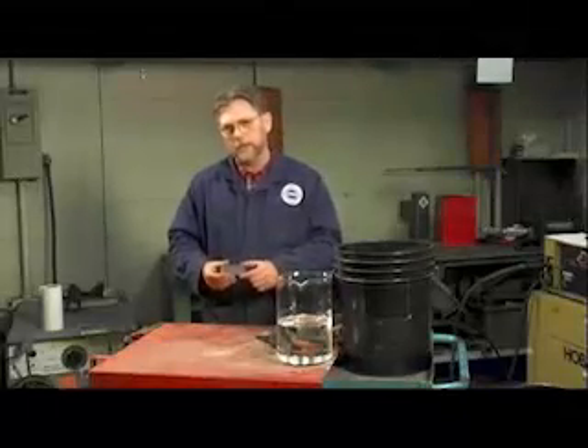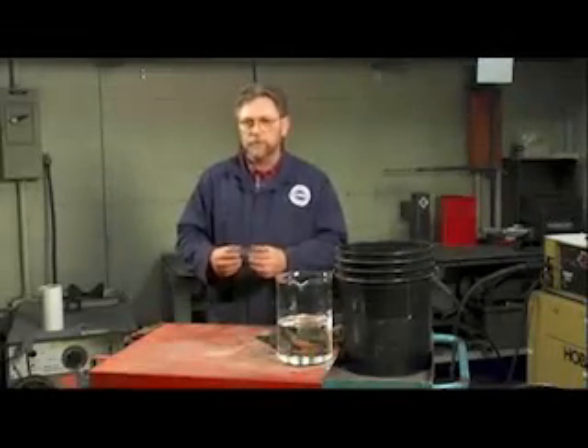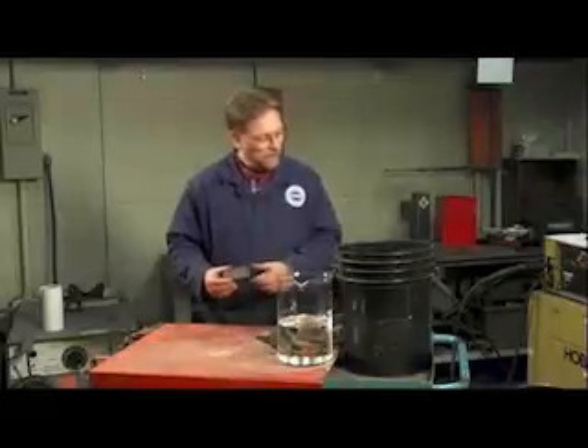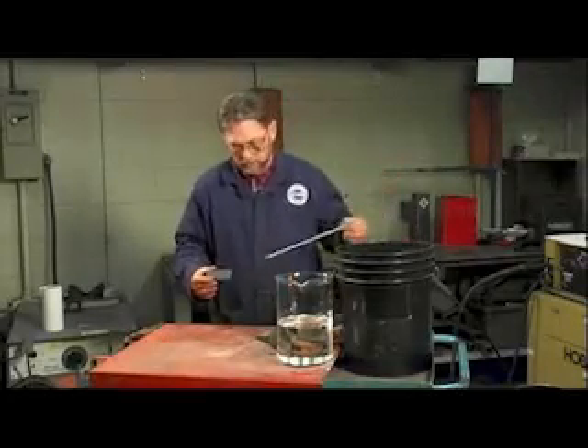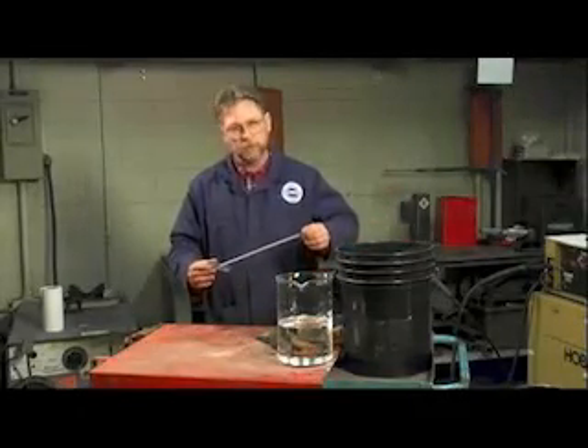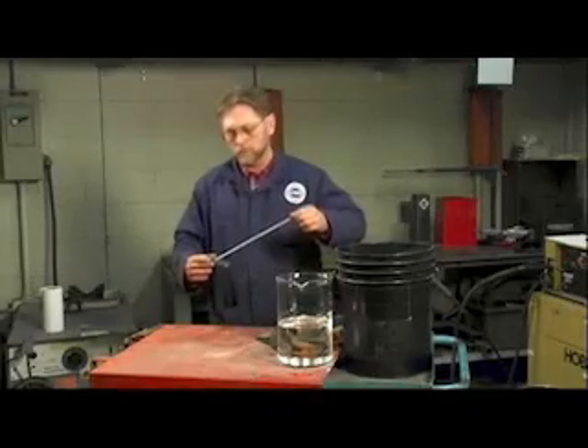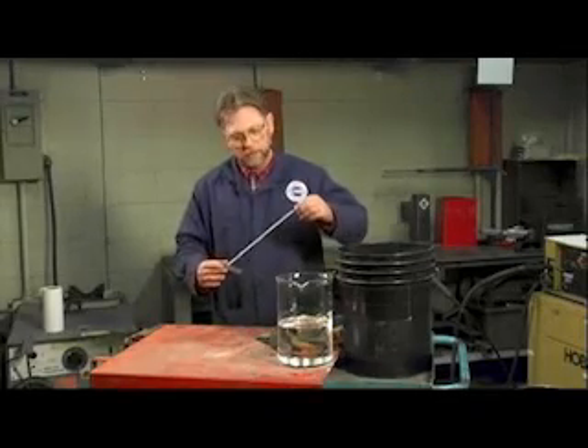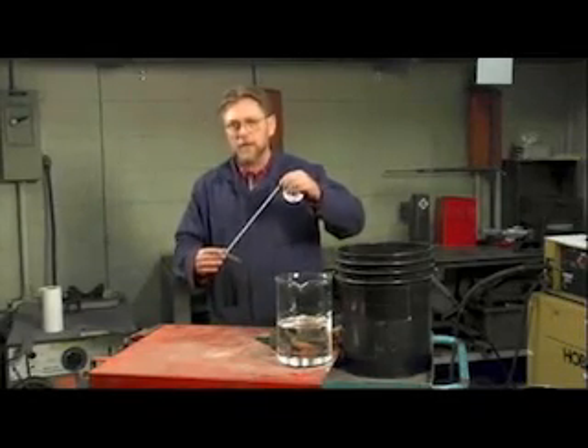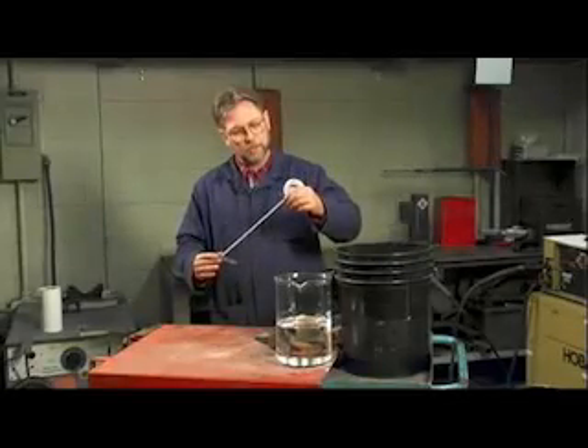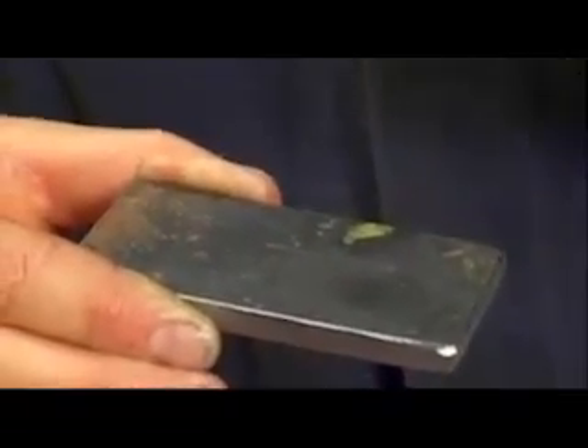We devised this demonstration to show the differences between the amount of hydrogen that evolves from different types of weld metals. Now this particular type that we're going to try now is called a basic type coating, or most commonly referred to as low hydrogen. It doesn't mean that it's simple, it's chemically basic. And chemically basic means that in the arc atmosphere there'll be quite a small amount of hydrogen present. And this is its goal, to keep that hydrogen out of the weld metal while still producing sound metal.